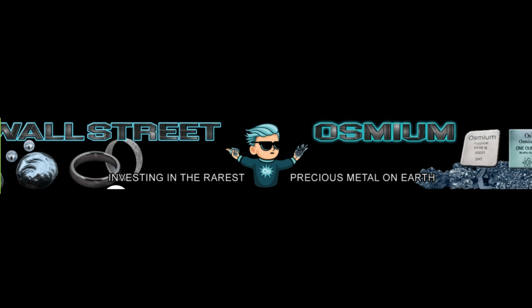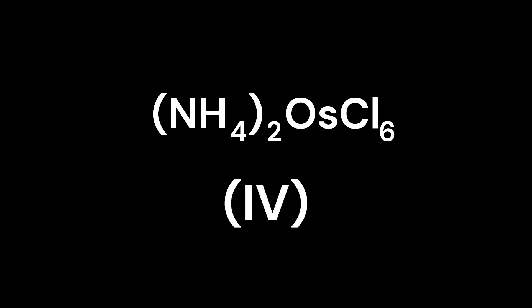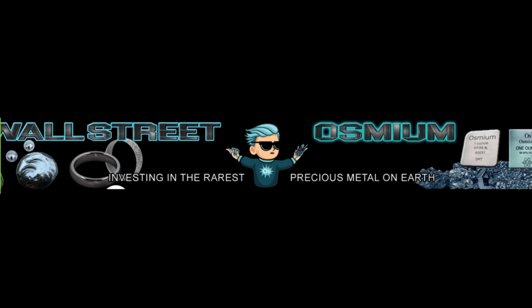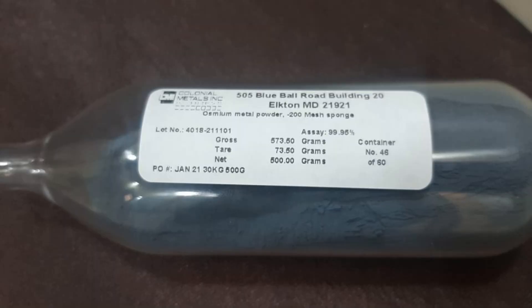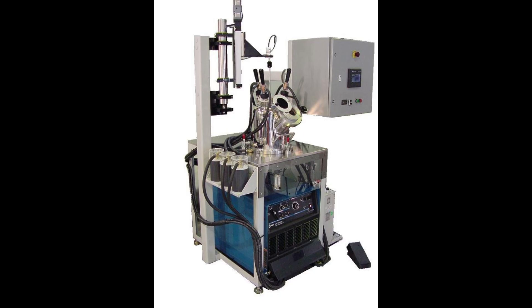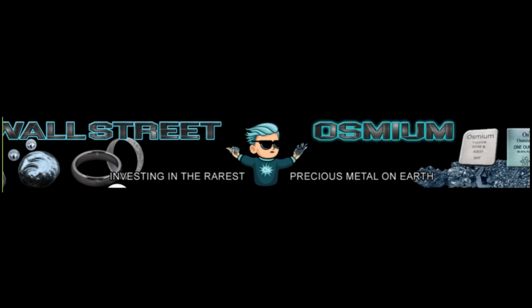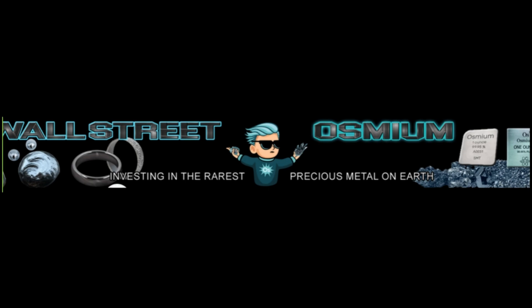Anyway, this sodium osmosulfite complex is then reacted with hydrogen chloride gas at dull red heat to produce sodium hexachloroosmate. This hexachloroosmate salt is then converted to ammonium hexachloroosmate via a double displacement reaction with ammonium chloride. This ammonium hexachloroosmate is arguably the best calcinable form because there's no oxygen attached to it. Calcining involves heating this compound to high temperatures in hydrogen gas, which converts it to osmium sponge. After this sponge is purified by reacting silicon dioxide impurities with hydrofluoric acid, it can be sintered or melted in an arc furnace to produce the lovely blue metal. This metal is the most oxidation-resistant form of osmium — very unreactive and completely safe to handle and wear as jewelry, despite what the rest of the internet may say about it. I very much hope you enjoyed this video, and thank you for watching.